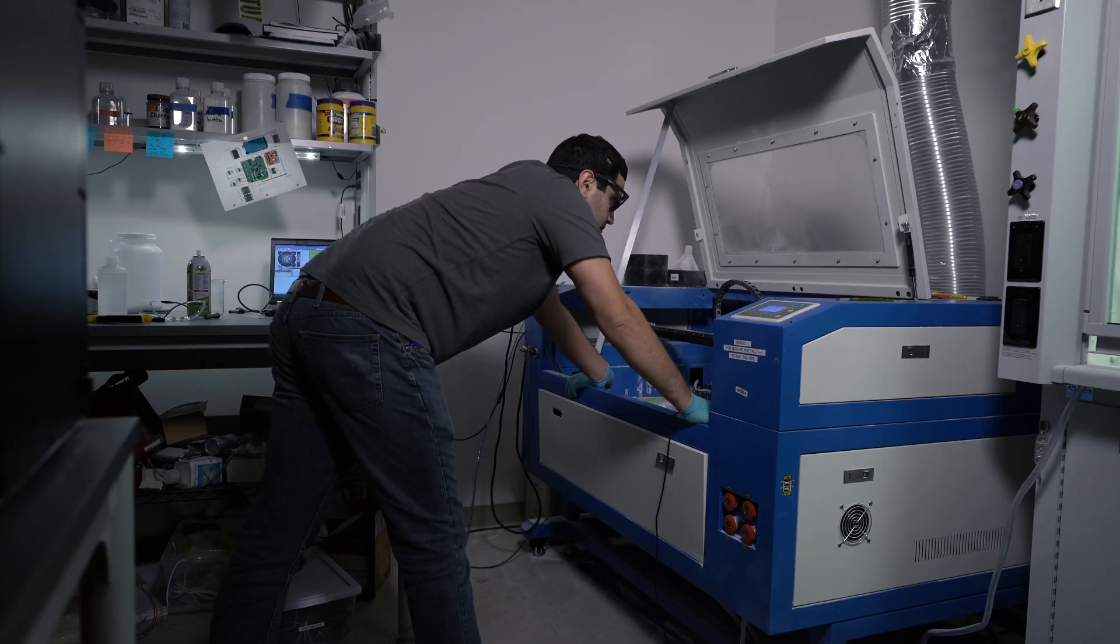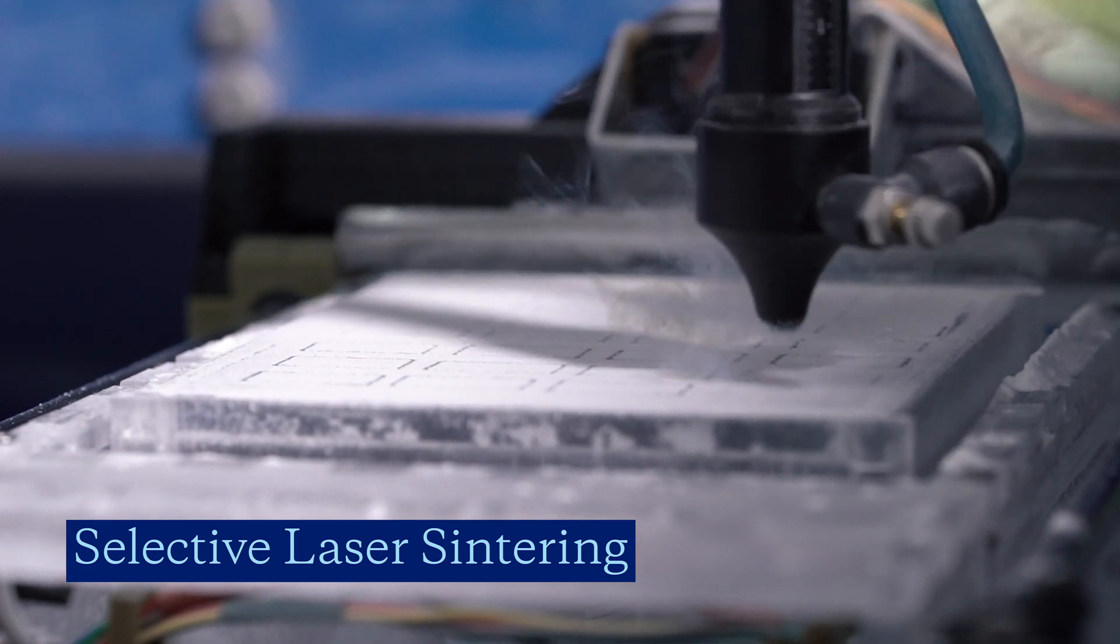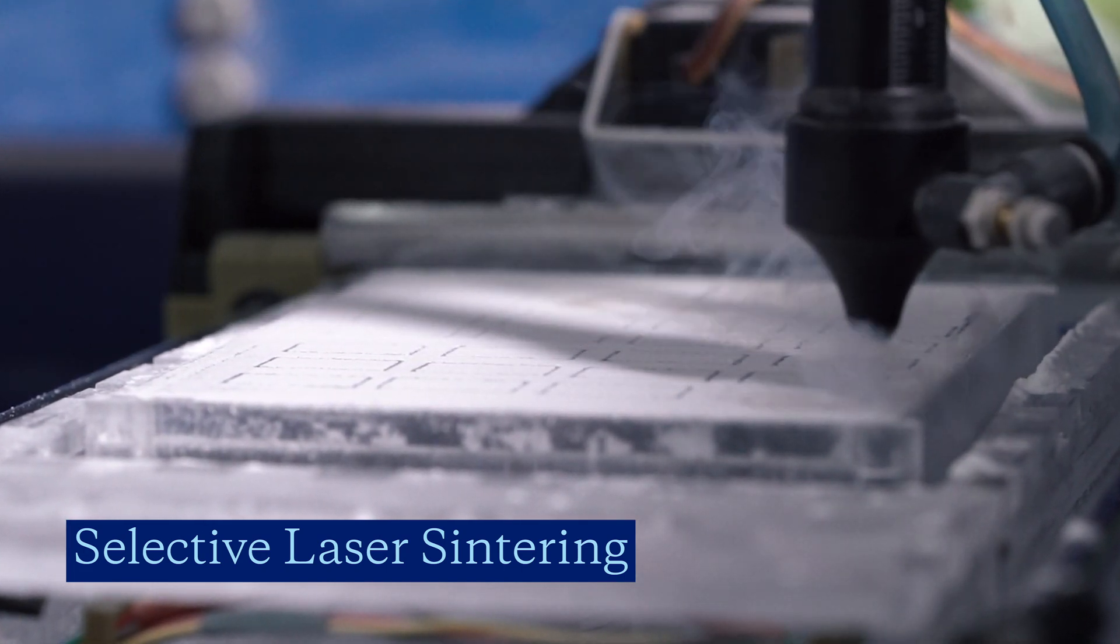So we're tracing patterns in these powdered sugars using a laser and locally melting these sugar particles together to form solid sugar structures.